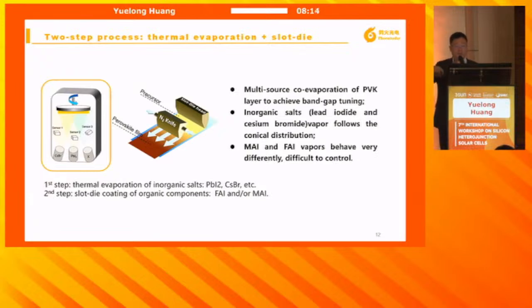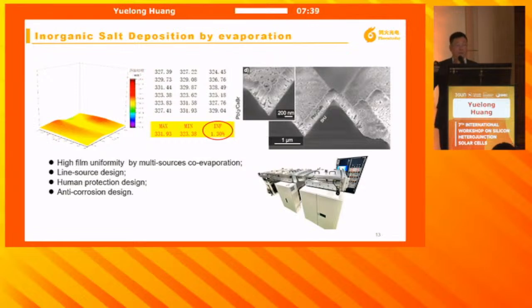Of course, multi-source co-evaporation of the PVK layer to achieve band gap tuning, everybody is doing that, but to make good evaporation for large area, then you again have problems. To make a small area record cell, you can use lots of techniques to do that, but to make large area, then it's difficult. So actually we have helped our partner to make a size of about 1 square meter. You put lots of wafers in the chamber and achieve 1.39% homogeneity to deposit all these kinds of inorganic salts or C60. So this is quite a lot of work.